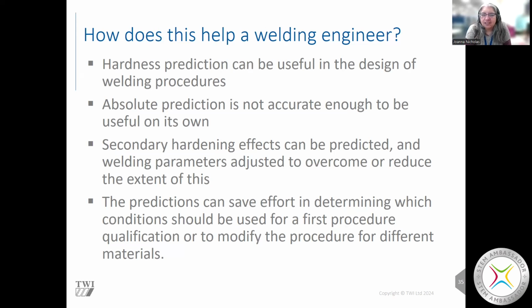The absolute prediction is not actually accurate enough, plus or minus 25, both for the neural network and for the empirical model. It is not accurate enough to be useful on its own, but we can predict what's going to happen if we change something. So we can say, oh, actually, because I've got this second weld pass, that means that the hardness is actually going to go up. If I choose different welding parameters or a different preheat, I can change it so that the hardness comes down. And is it below the level that I need, those critical hardnesses for cracking? And that can save quite a lot of effort.